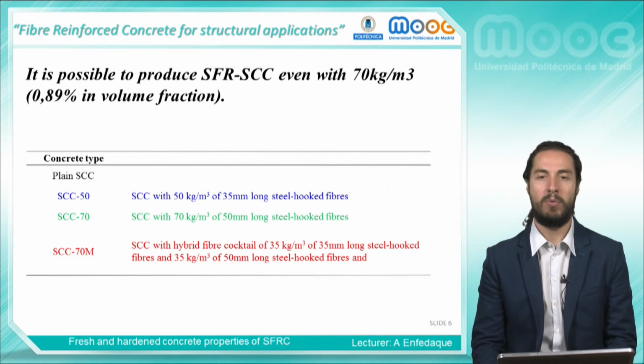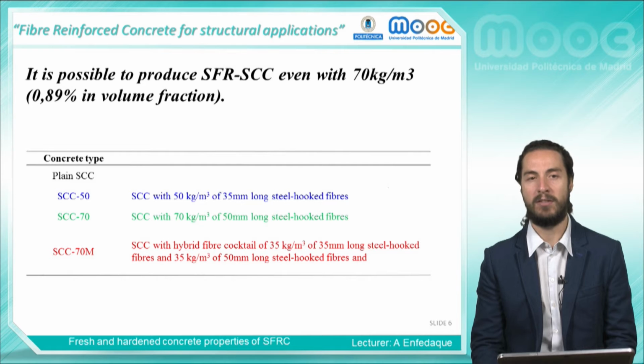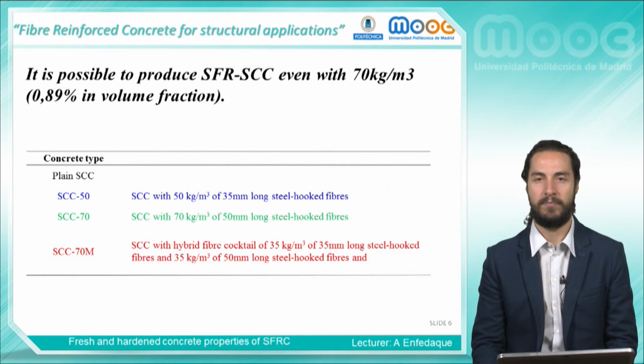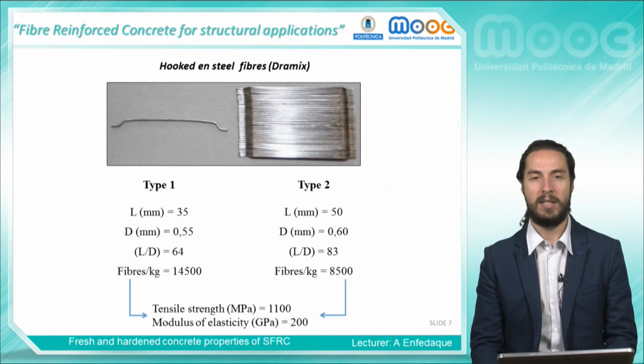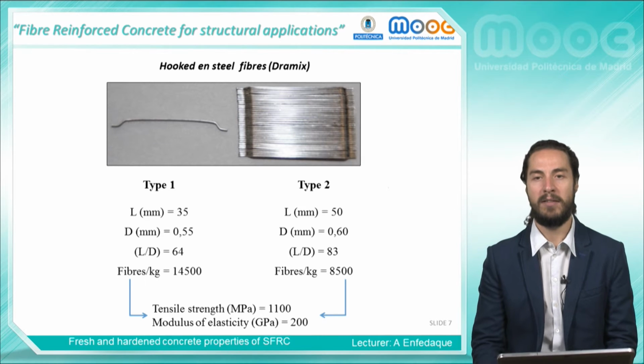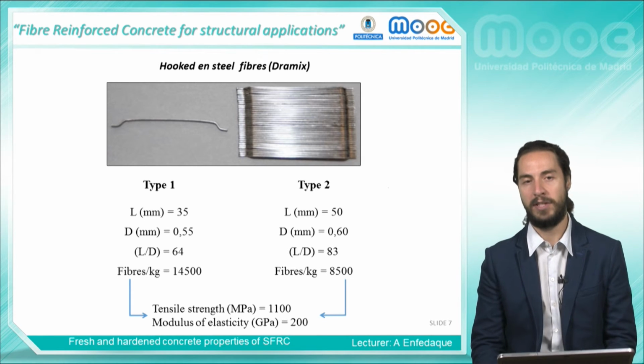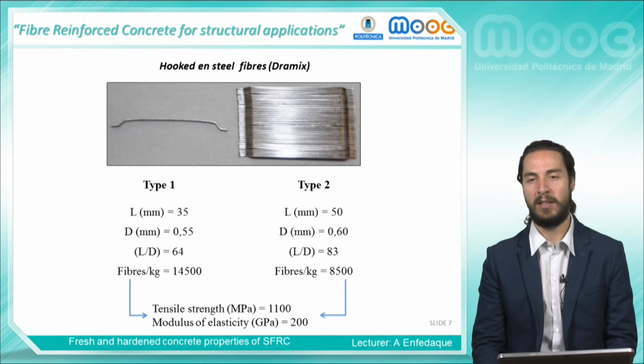That is to say, we will compare steel fiber reinforced self-compacting concrete with various dosages to assess the influence of steel fibers in fresh and hardened properties of the concrete. One mixture was manufactured with 50 kg per cubic meter of 35 mm long steel hook fibers, and another one with 70 kg per cubic meter. In another mixture, the two types of fibers were mixed in equal weights up to 70 kg per cubic meter. The two types of hooked end steel fibers chosen mainly differ in the fiber length and therefore in the aspect ratio. Also, the number of fibers per kilogram changed. The overall properties of the fibers can be seen in the slide.